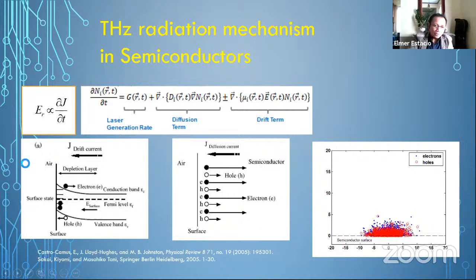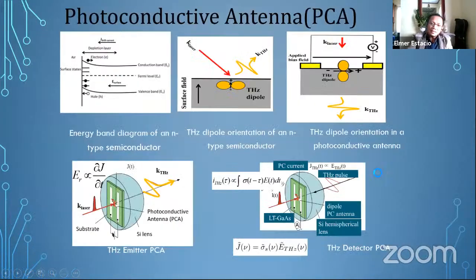So right now, we're looking at how electrons move from the surface to the bulk. However, the terahertz generation may be made more efficient if we apply a lateral bias on the semiconductor, and instead of just the electrons moving from the surface region to the bulk region, we may force them to move in the lateral direction. In this case, we rotate the plume of the terahertz radiation, not in this diagonal direction, but in the forward direction. And this is realized by the fabrication of photoconductive antennas, where we deposit metals on the semiconductor surface, and if we apply a bias that will force electrons to move laterally instead of normally with respect to the surface, then we generate more efficient terahertz radiation.